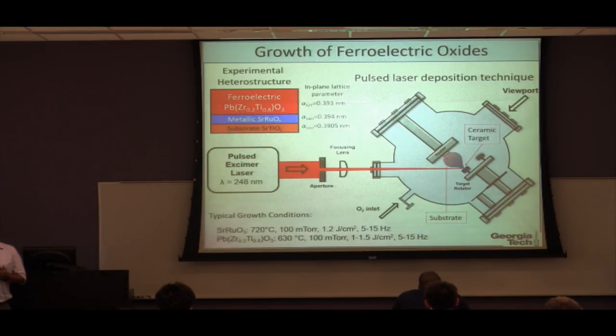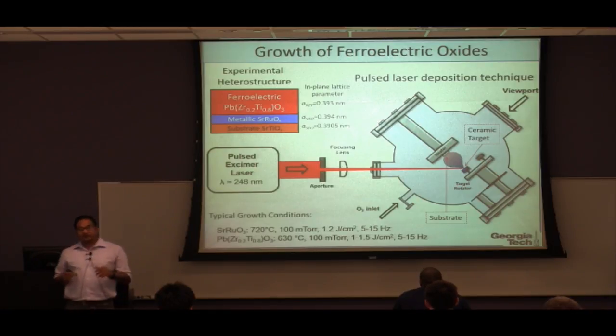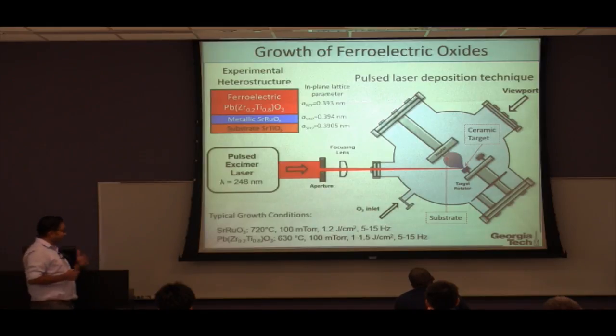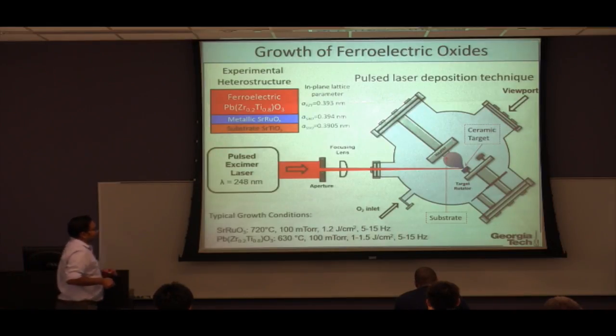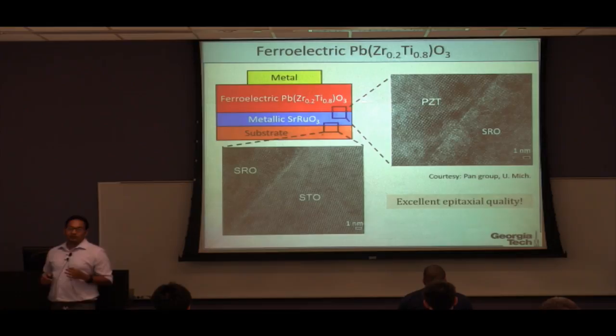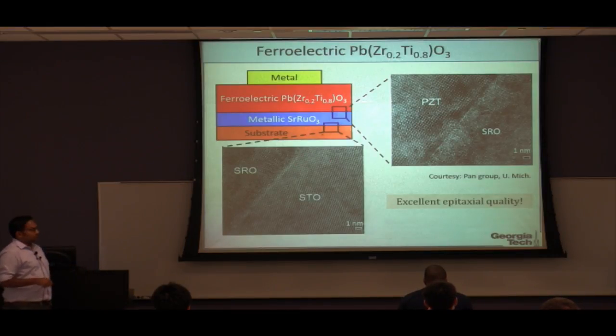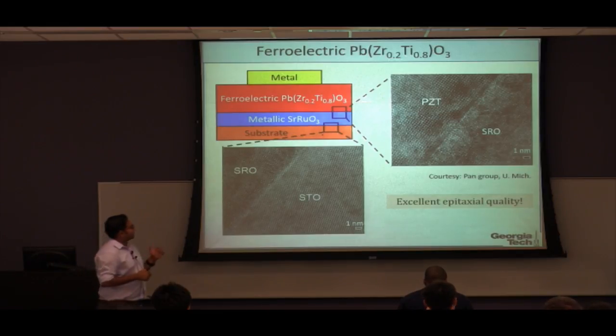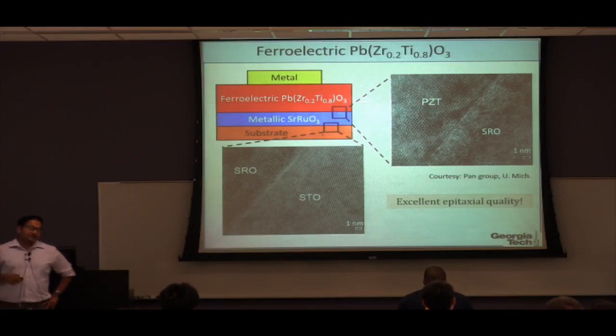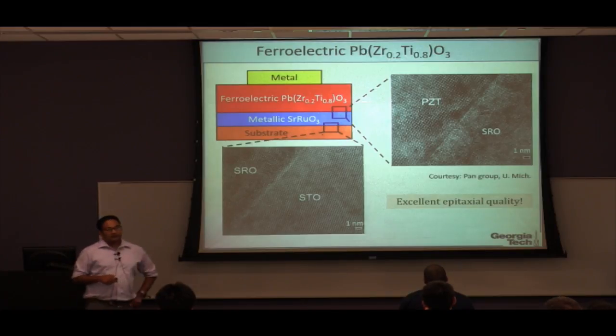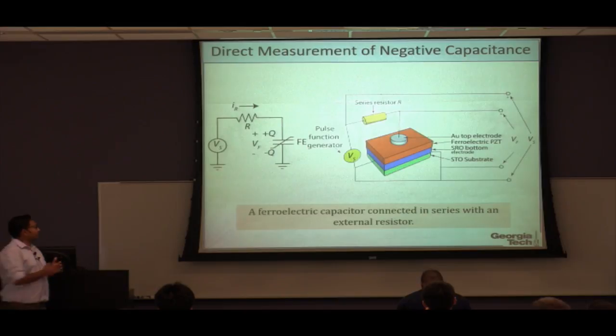So this is actually what I did in my 4 years of my PhD. I was just spending time turning knobs and letting the oxygen in, changing the pressure and all these things. The growth of this material is kind of tricky because there are a lot of issues with reproducibility and other things. But at the end of the day, what we ended up with was very high quality epitaxial ferroelectric films. And these are the two TEM images of this material system that we are showing. The important thing is that the material is near perfect and the interfaces between the different material systems are also perfect. So that was another key to our results, because we could grow very high quality ferroelectric materials.